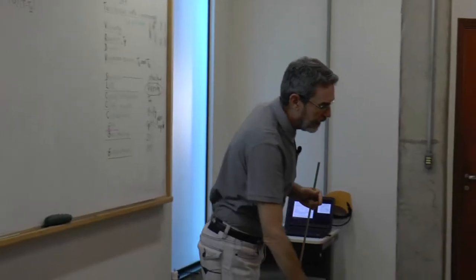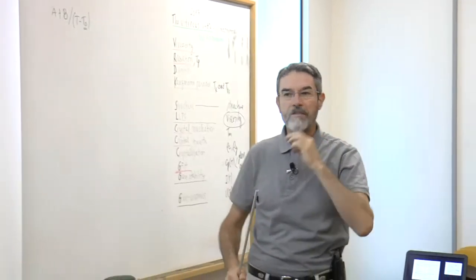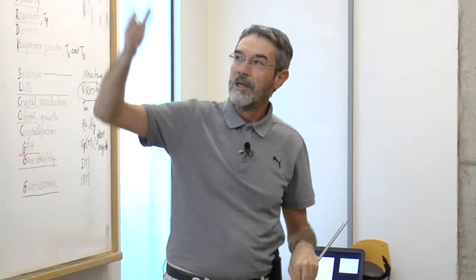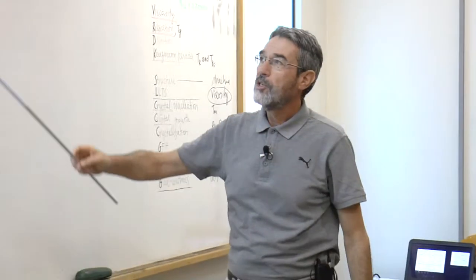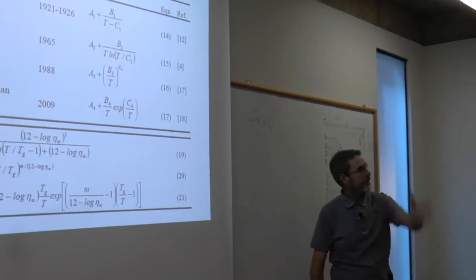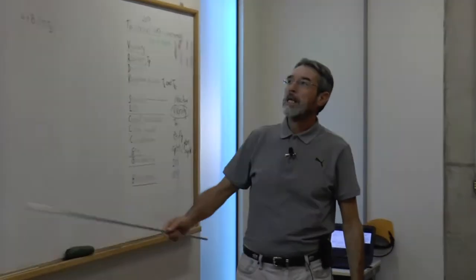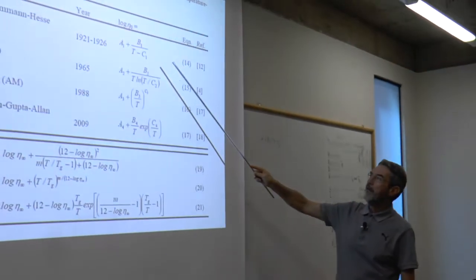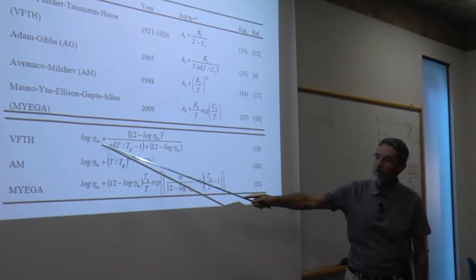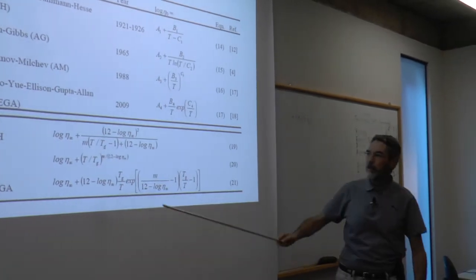When the actual sample temperature tends to T0, the viscosity tends to infinity. I'm not saying that this happens, but this is the prediction of that particular equation. These other two equations here do not predict a divergent viscosity. Anyway, if we rewrite this equation in this particular form, you see that eta infinity is the value at very high temperatures.